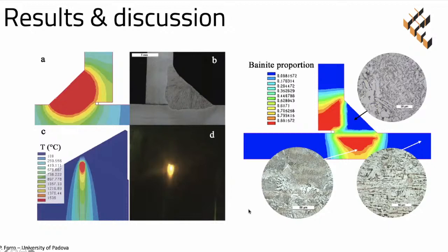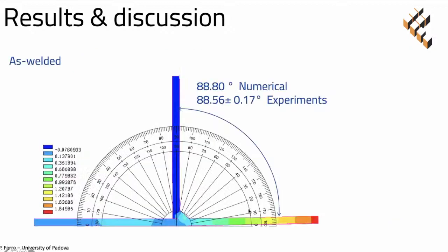We compare the angular distortion of the welded joint calculated by experiment and numerical analysis, and we found a good agreement between the two measurements in as-welded condition.